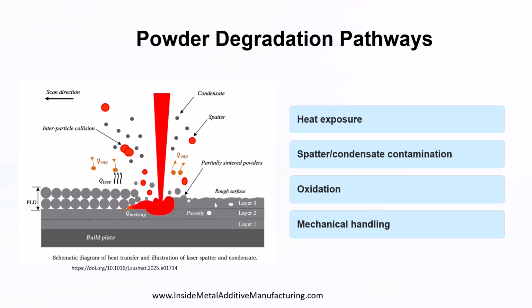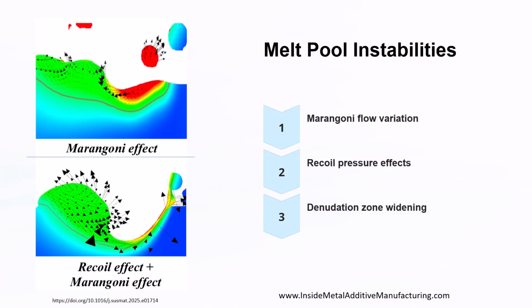As the build progresses, oxidation increases, especially in alloys like titanium. Oxygen-rich spatters and condensate shift the powder's chemical composition, which affects everything from melt pool behavior to final mechanical properties. And speaking of melt pools, recycled powder fundamentally alters melt pool stability. Changes in surface chemistry and particle morphology influence Marangoni flow, recoil pressure, and even the width of the denudation zone around each track. The melt pools become deeper but more erratic, and erratic melt pools mean one thing: more porosity, more variability, and a greater risk of defects.